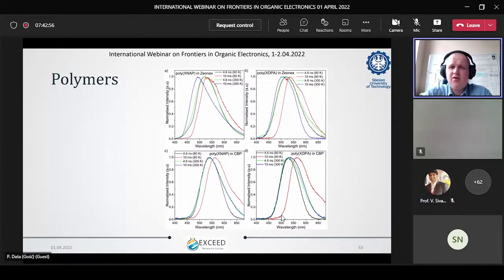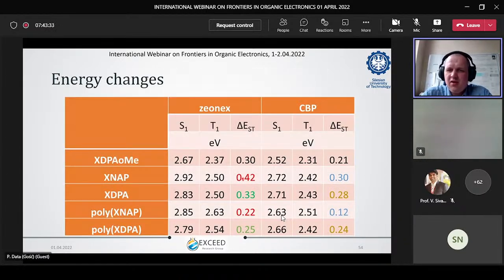So what happened for our polymers, where we had our donor, we had our small molecules XNAP and XDPA, but in the polymer form, when we compare our phosphorescence, it is smaller. In the monomer, if we call it like that, we had like 0.4. Here we drop that by half. If we go to the CBP, the same. Our ST gap drops, which means we got more and more efficient emitter.